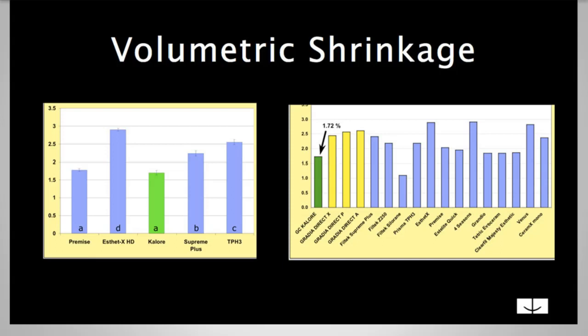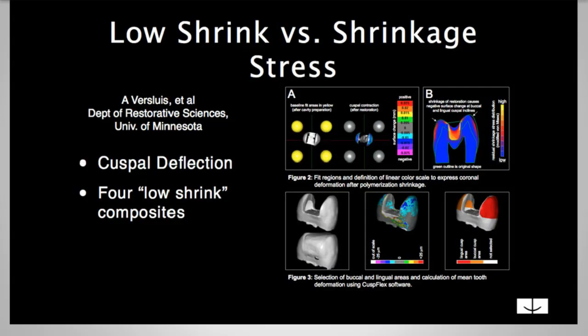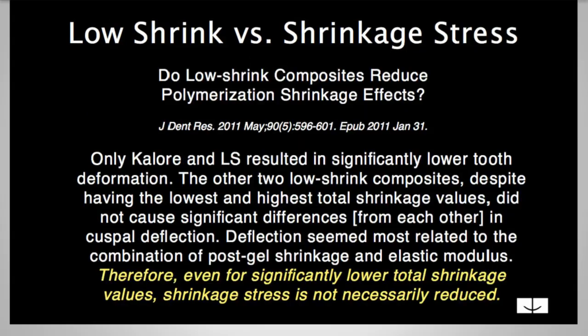So there was this study done about low shrink versus shrinkage stress. What they did is they looked at cuspal deflection, essentially bonding a tooth and then filling it with the packable resin and seeing how much cusp deflection there was for 4 quote-unquote low shrink composites. What they found was interesting in that all of the composites were different in how much they shrank. 2 were significantly lower than the others, but they didn't necessarily have lower shrinkage stress.